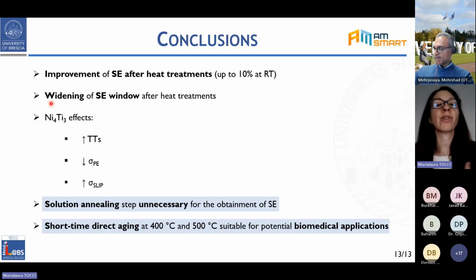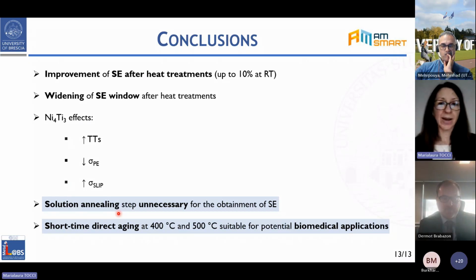This was found true for all the treatments analyzed, so also the, let's say, innovative one, the direct aging treatment carried out for a short time. It was a 15 minutes treatment, indicating that more interest and further studies can be carried out, since this seems an interesting approach for potential biomedical applications, and that, as we said, we can work on treatments that skip the solution annealing step, also in order to reduce the treatment routes and make them more sustainable and cost-effective. And with this, I conclude.